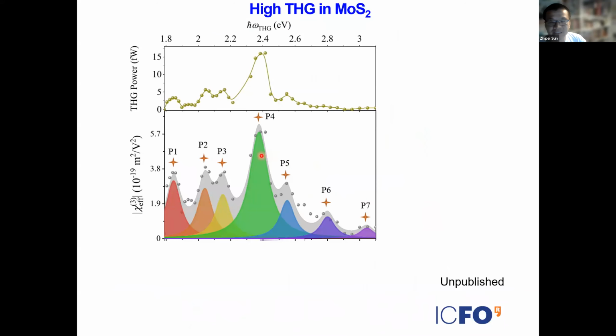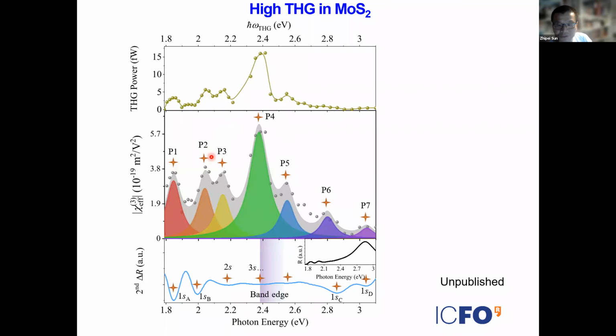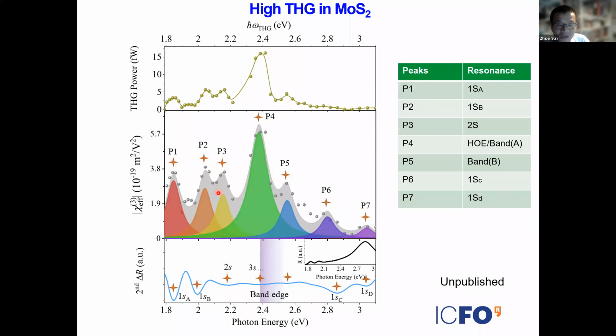To fully understand this, we measured the third harmonic generation as a function of the third harmonic generation wavelength, and then extracted the chi3 of the MoS2 at the different wavelengths. We could easily find 7 resonance peaks with a much larger third harmonic generation efficiency. To understand this, we compared these results with the linear reflection spectrum, the second order differential reflection spectrum. We can clearly see that all those peaks correspond to different excitonic resonance states inside of MoS2.